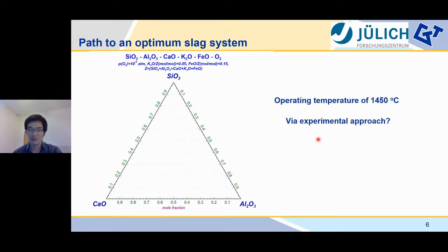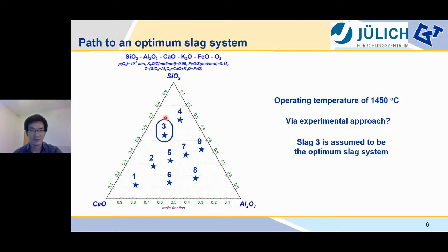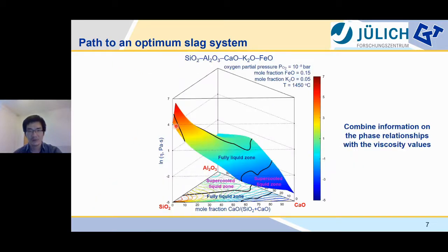By doing experimental work, viscosity measurements as well as corrosion tests are both really time-consuming. Also, it's not possible to consider all possible compositions. So in the end, we may select a limited number of samples. For example, here we select eight samples for this five-component system. After experimental work, we may find out that slag three is the best one. But please keep in mind, the result obtained here is not a global optimum slag system, because we only compare these eight samples. So it's necessary to do some precalculations, for example by using FactSage.